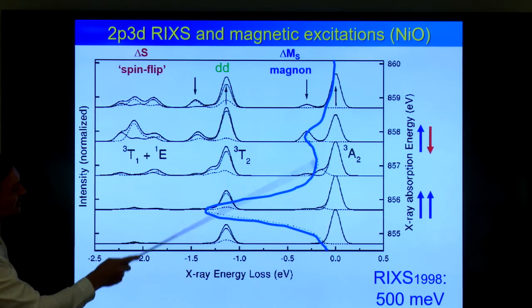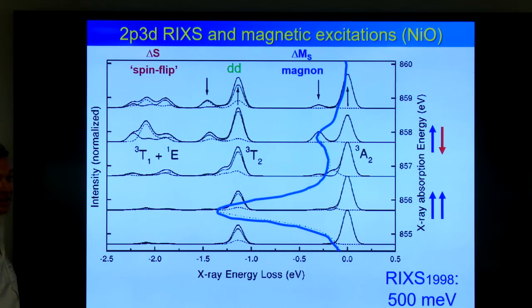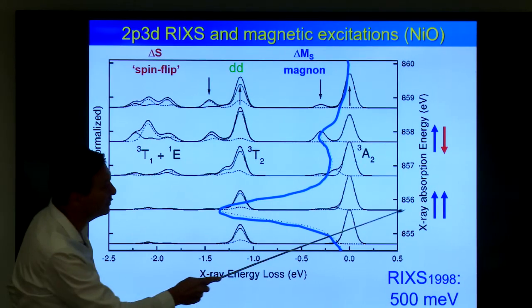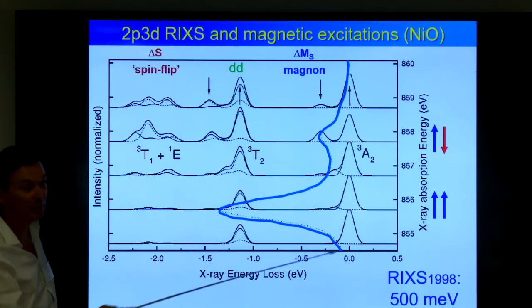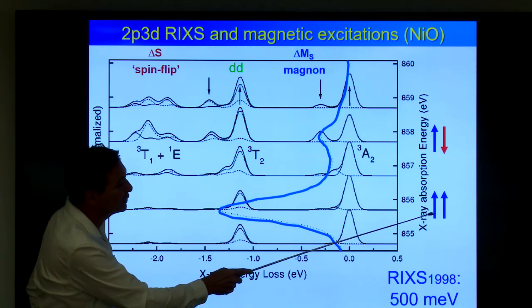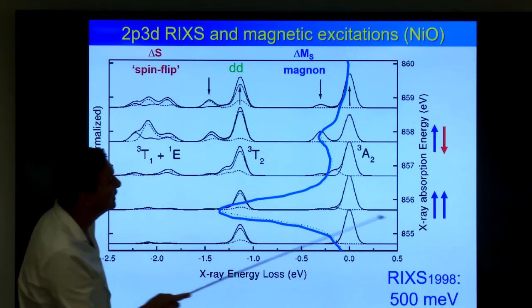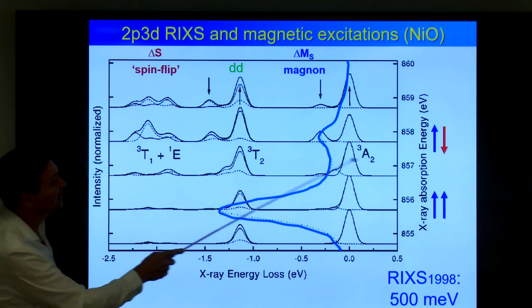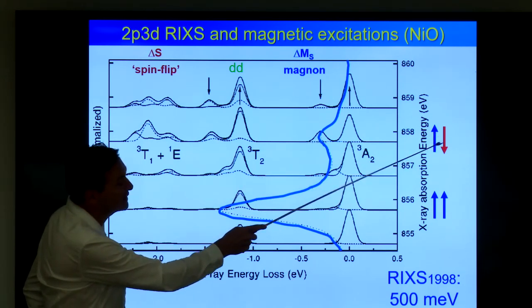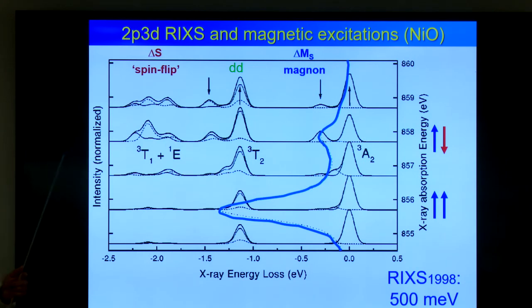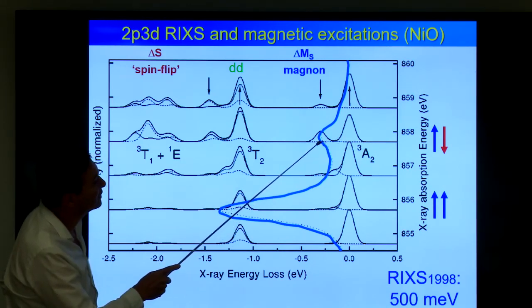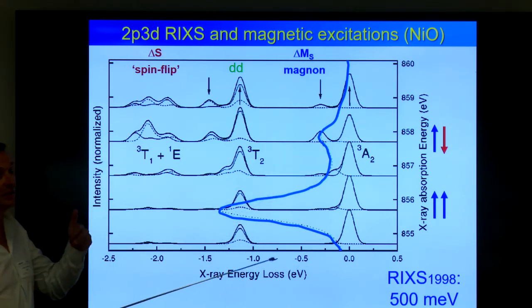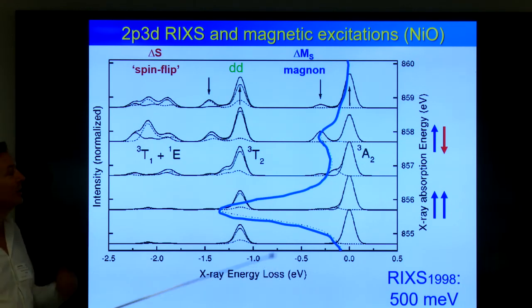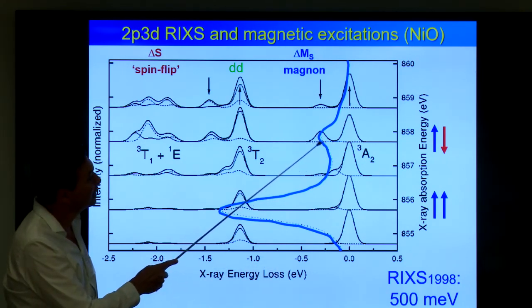So why is it visible there and not there? If your ground state is a triplet, in the intermediate state, the main peak in X-ray absorption is a triplet. That means that the spin of the core is parallel to the spin of the valence hole. But the satellite is a singlet. So the satellite has a singlet state of the core hole spin and the valence spin. And that means that the satellite doesn't have any memory of where it comes from. So it can go back to the ground state, or it can go back to a state where it flips both spins. So you suddenly have 2 spins down instead of 2 spins up. And that gives the superexchange energy and the magnon peak.